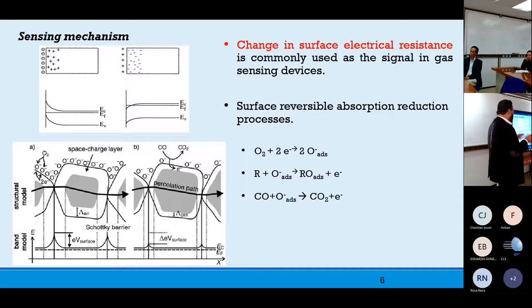We know that the surface of a semiconductor is oxidized because of the interaction with the oxygen that is present in the atmosphere, and this causes the surface of the semiconductor to have a positive charge. When a reductant gas such as carbon monoxide interacts with the surface of the semiconductor, the charge changes to a negative charge, and this change of the charge on the surface can be measured for detecting carbon monoxide. But what is the chemical process that happens on the surface of the semiconductor?